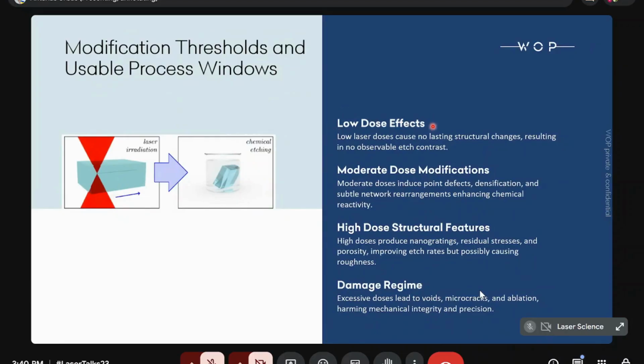If you put too little energy, you might not achieve a modification big enough to be etched selectively. With moderate energy, you can make modifications that can be efficiently and smoothly etched. If it is a little bit too high, then you can build nanogratings or cracks, which help you in etching, but it makes your shape irregular and very often unpredictable.